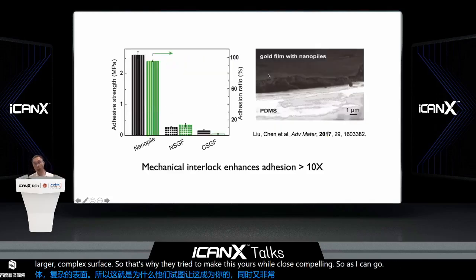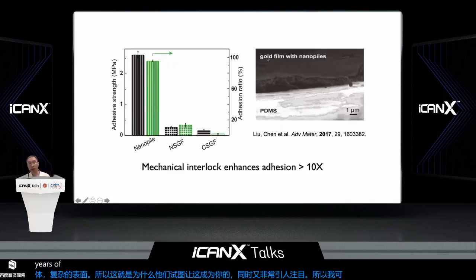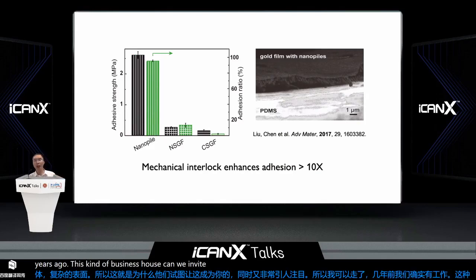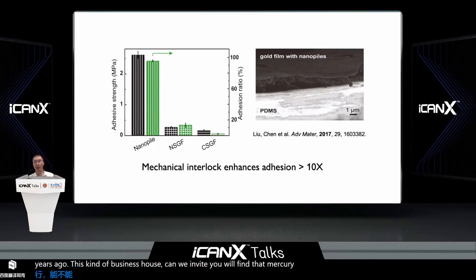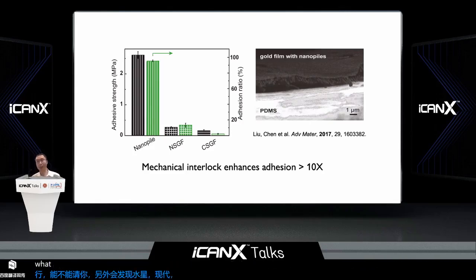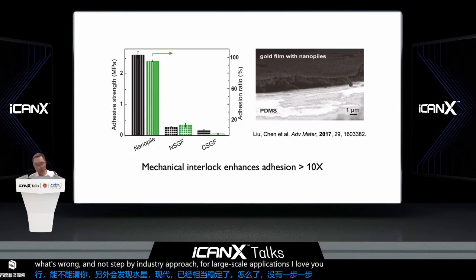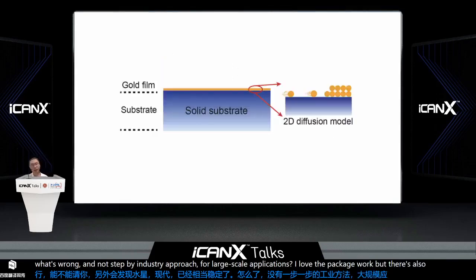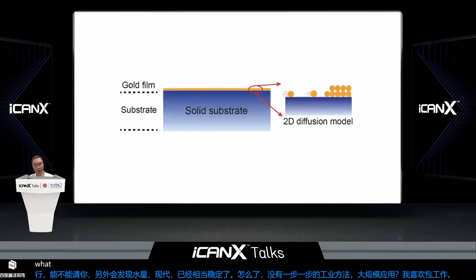We did work a few years ago using a gold film with nanopiles that can be embedded in the PDMS. We found the mechanical interlocking enhanced adhesion by more than 10 times, and it was pretty stable. Unfortunately, although this approach works well, it was not accepted by industry. No one will take this approach for larger scale fabrication, although we published the work. But it also pushed us to think about what more we could do.